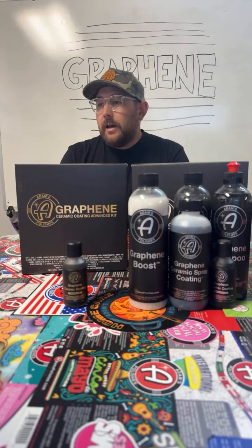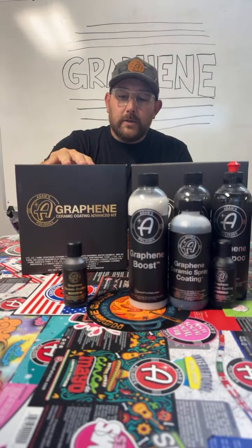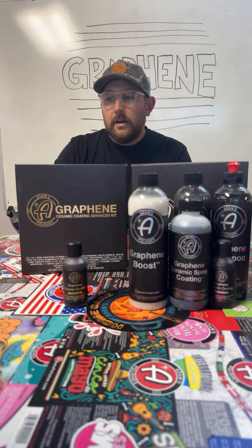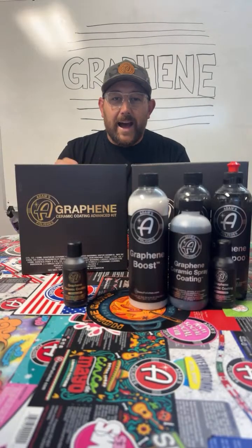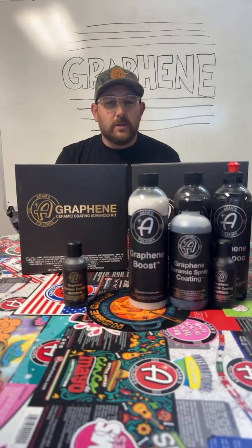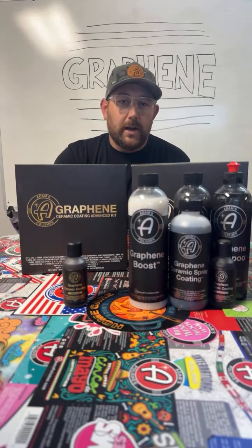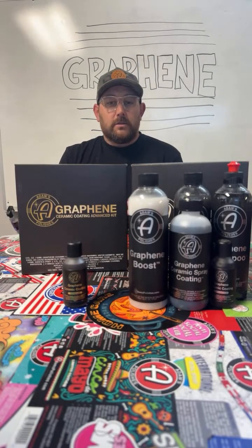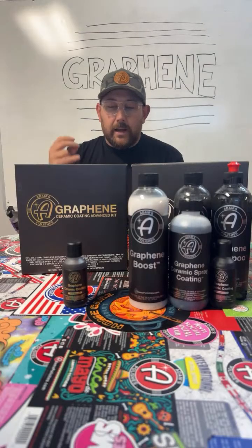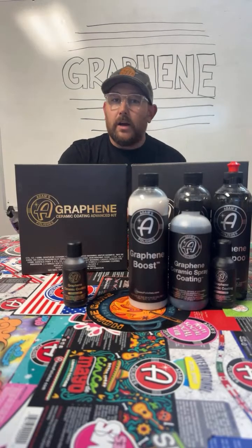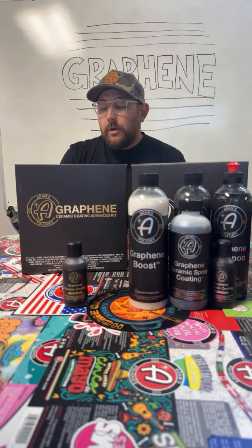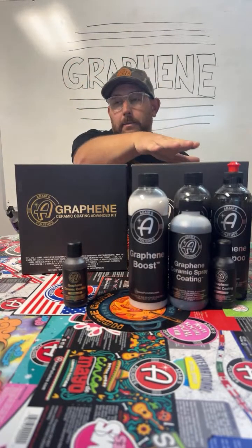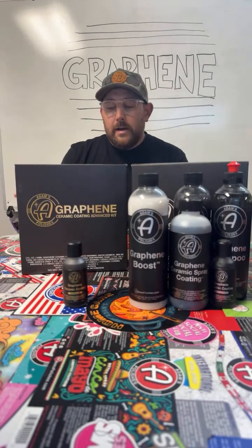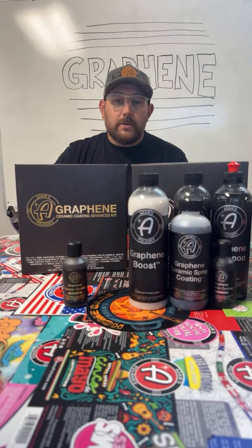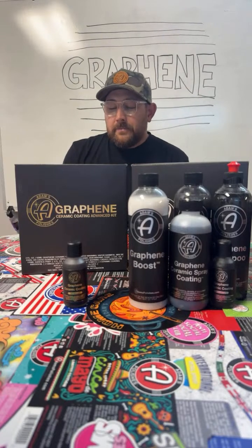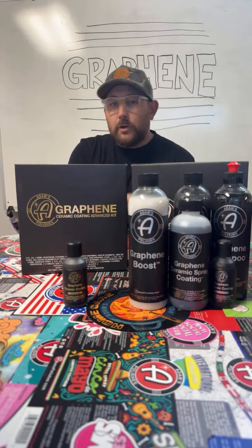We start testing it. I'm telling you guys, testing the first iteration of Graphene Ceramic Coating Advanced, it failed a lot. The application was really, really difficult. It was so concentrated that you had to work in such small areas, and it cured almost instantly, so it was really hard to wipe off. We would put it on and wait a normal wait time like on regular graphene ceramic coating, and it was like, oh, can't wipe it off. It's too sticky, too hard to get off. So we kind of tabled it for a little while.